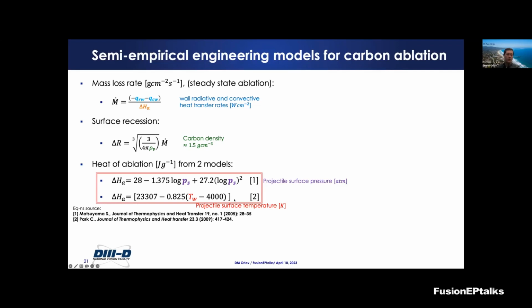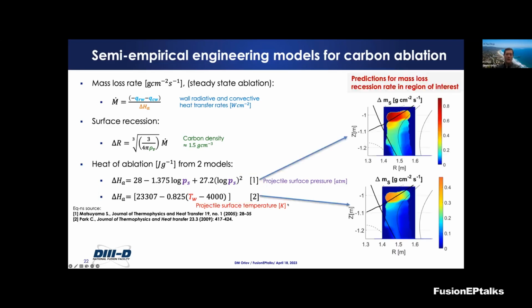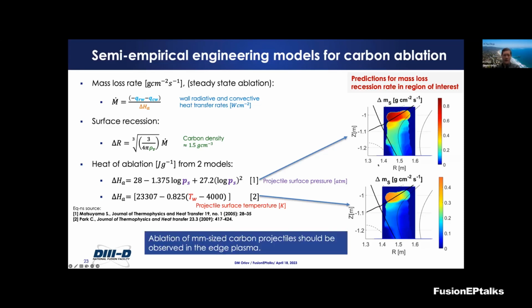So those would be the two models that we will be testing in these experiments. Using these two models, we can do some simple predictive simulations and estimate how much mass we'd be losing in the divertor region of the DIII-D tokamak based on a model discharge from before the experiments. That modeling suggested that in L-mode conditions, we should see ablation of millimeter-sized carbon pellets in the edge plasmas.